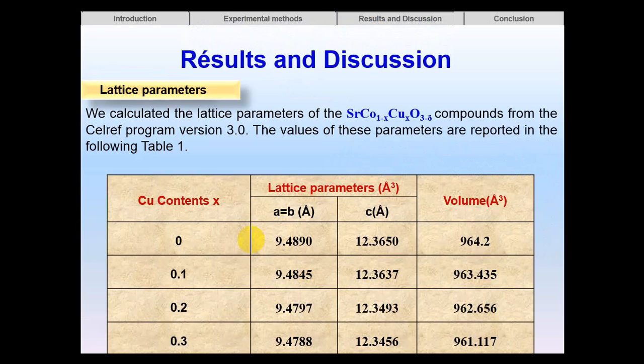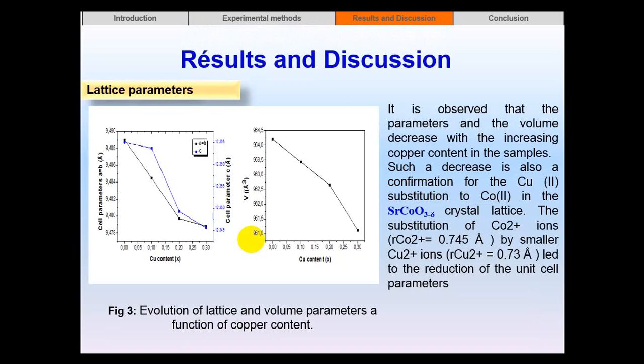For the lattice parameters, we calculated the lattice of different samples using the Celref program version 3. The values are in the following table, and figure 3 shows the evolution of the lattice and volume parameters as a function of copper content. It's observed that the parameters and the volume decrease with increasing copper content in the sample. Such a decrease is also a confirmation of the Cu2+ substitution for cobalt in the SrCoO3-δ crystal lattice.